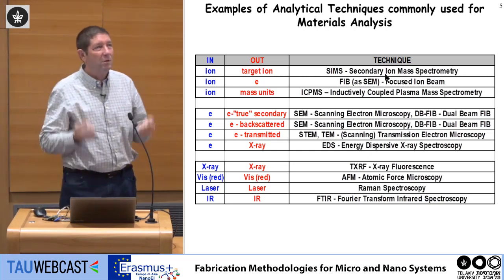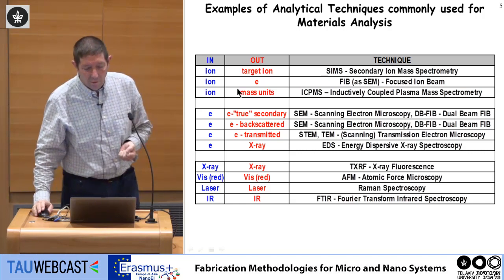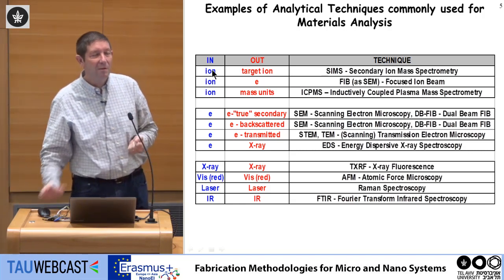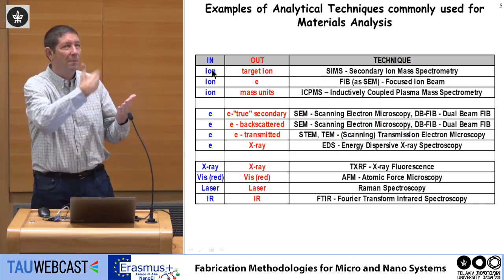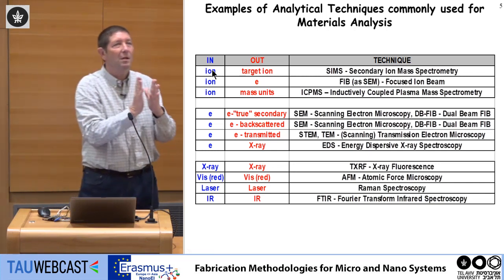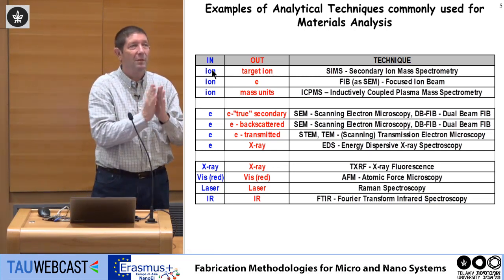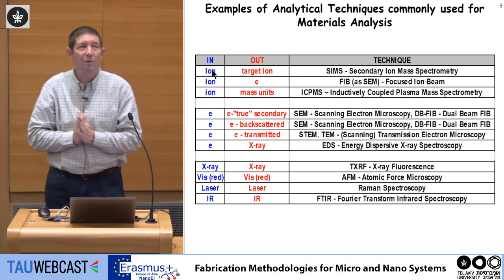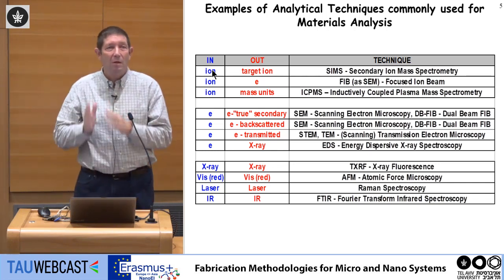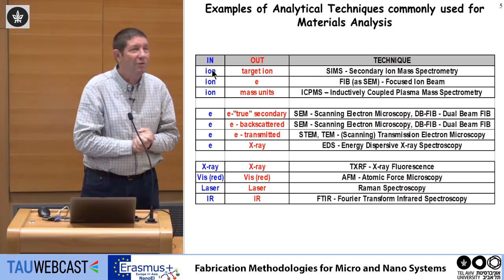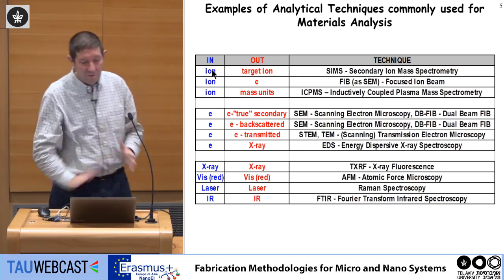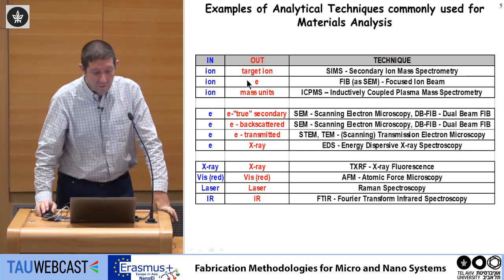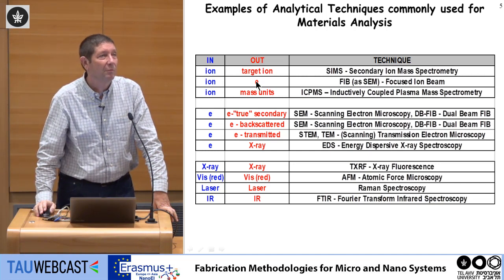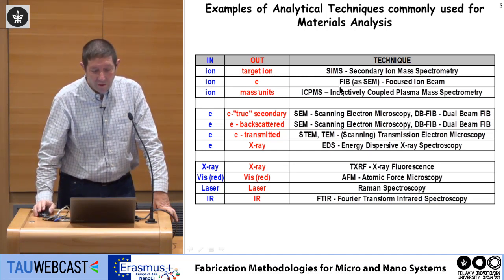So I can measure the composition, and since I can do etching during the measurement, I can actually get the profile of the material. I can get the profile of the dopants or the materials or the composition, if it's an alloy, as a function of distance. I can apply ions and measure electrons which are emitted because of the collision. This is in a process called focused ion beam.